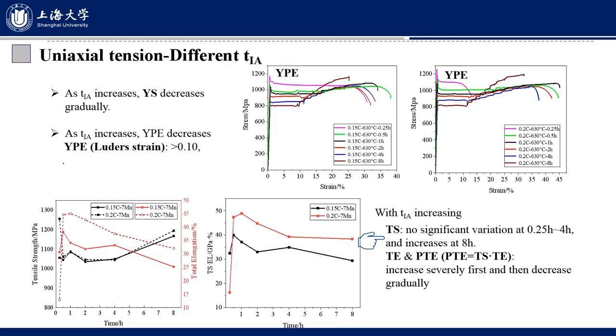This is the result of the uniaxial tension test at different intercritical annealing time cases. As intercritical annealing time increases, yield stress decreases gradually. This slide shows the mechanical properties of the steel for different intercritical annealing time cases. As intercritical annealing time increases, yield stress decreases gradually, and yield point elongation also decreases, but yield point elongation of the steel is larger than 10%.